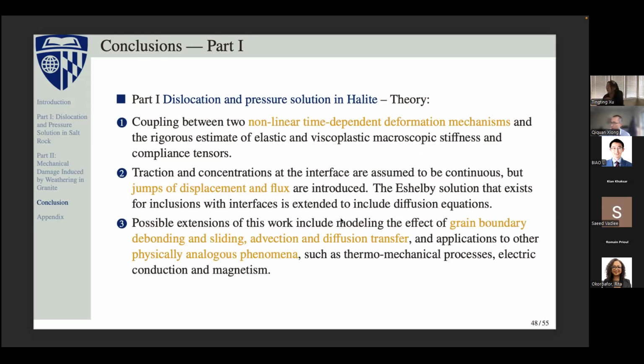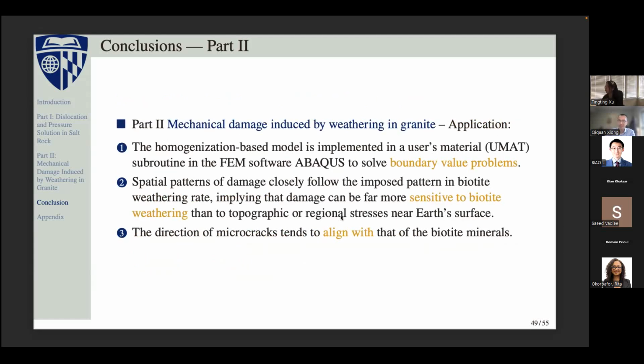And in terms of the theoretical part, it's actually not limited to the application to the halite, but it provides a pretty general homogenization framework for this kind of nonlinear and time-dependent problem. And it can also consider the jumps of the displacement and the flux inside this problem. That is pretty innovative. With that, this model framework is expected to simulate all other similar phenomena, such as grain boundary debonding, sliding, dissolution, and diffusion transport. So we can expand this model to consider other problems.